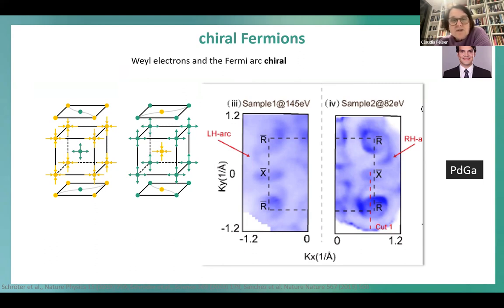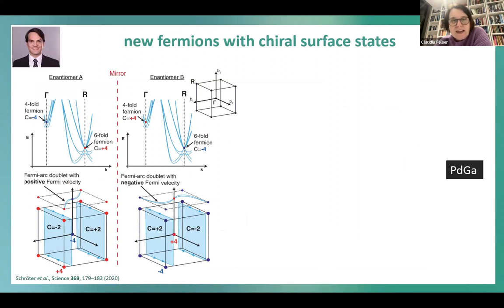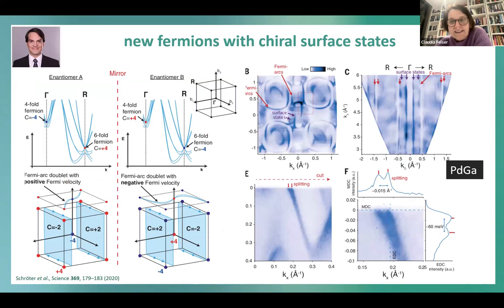So the next slide, this is a little bit for experts, maybe, needs two clicks, but it led to a very nice paper. So one thing was that people said the topological number in this material is different. So you have Chern numbers of plus 4 and minus 2 in one chirality of the crystal, and in the other it's also swapped. And this we could show simply by seeing that the surface states are split thanks to spin-orbit coupling, and that they are really surface states.